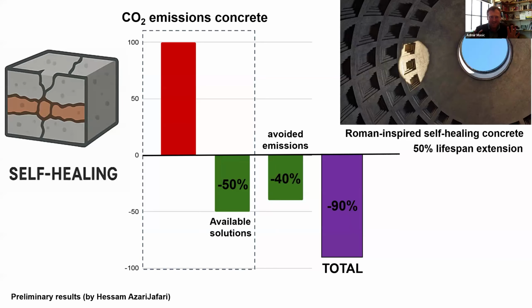Now, if we look at that general picture where we have 100% CO2 emissions associated with cement production, and we integrate available solutions of 50%, and now introduce the functionality of self-healing into everything we build, we create 40% of avoided emissions, and that totals to minus 90% total saving on emissions. And that really brings us very close to carbon neutrality by just giving a self-healing characteristic.